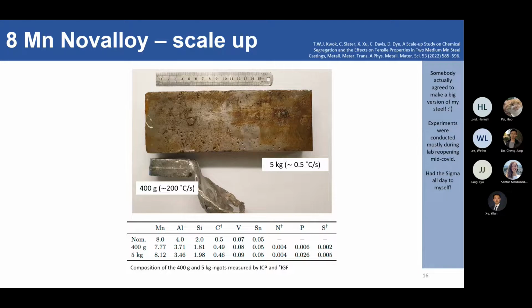Same steel. We were very excited with it. Yeah, first medium manganese steels that actually worked. So we went to find our good friends in Warwick to produce a large ingot for us here. So we're trying to scale up. We made a 5 kilogram ingot here compared to our little baby 400 gram ingot. And if you remember what I said about high manganese steels, that it was very difficult to homogenize, right? So it's been assumed, but nobody actually went to test that if you have a medium manganese steel, you have less manganese, so less segregation, you know.